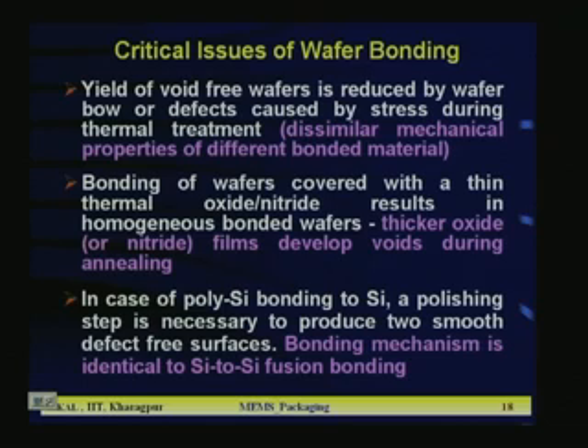Now, there are several other issues. Those are namely, the yield of void free wafers is reduced by wafer bow or defects caused by stress during thermal treatment. Stress generation between the surfaces is obvious during fusion bonding at higher temperature. If you go for bonding at 1000 degree centigrade or more, and if the mechanical properties, meaning thermal expansion coefficient, of the 2 layers are dissimilar, such as silicon with glass or silicon nitride with glass, and the expansion coefficient does not match properly, then there is a chance of wafer bowing, and that creates defects which will ultimately create voids and yield will be low.